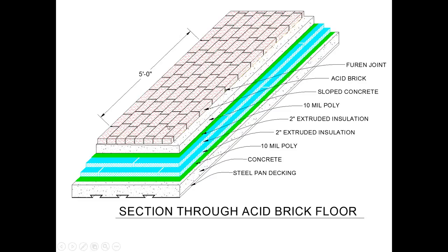So you can see here we have acid brick floor, we have sloped concrete topping. The green is a layer of 10 mil poly. We have 2 layers of 2-inch polystyrene insulation, a layer of 10 mil poly, and then concrete with a steel composite deck. Well, to say the least, this structure leaked.